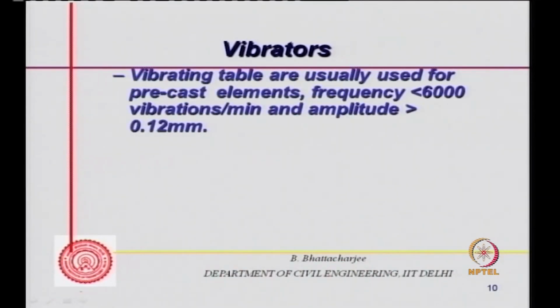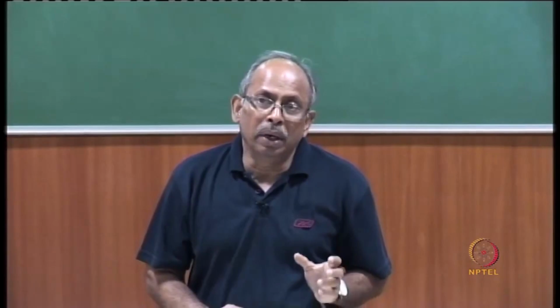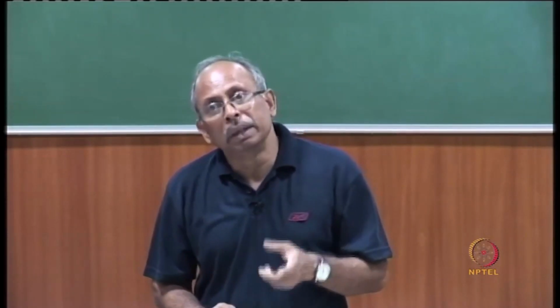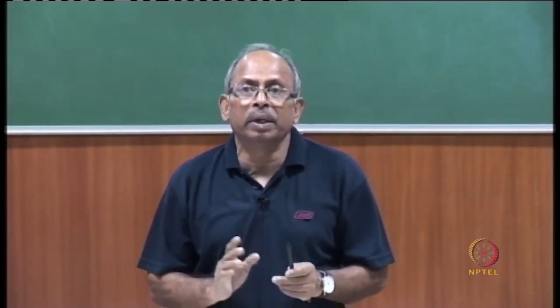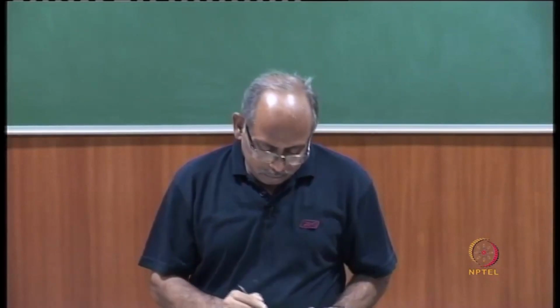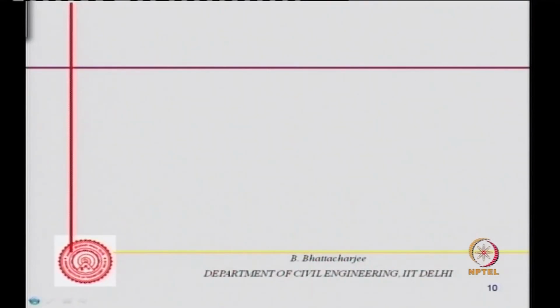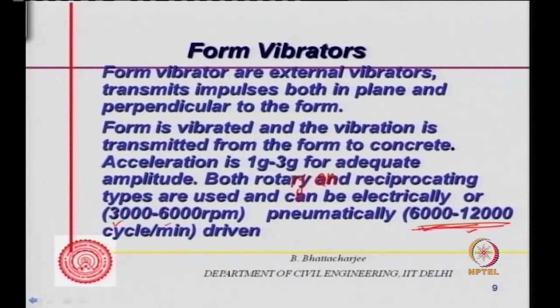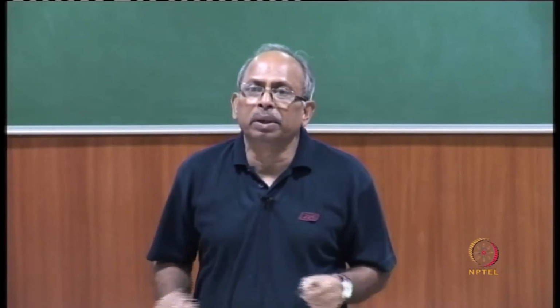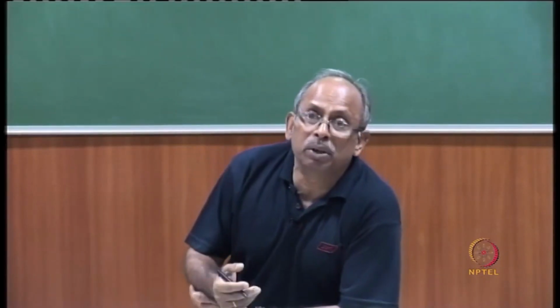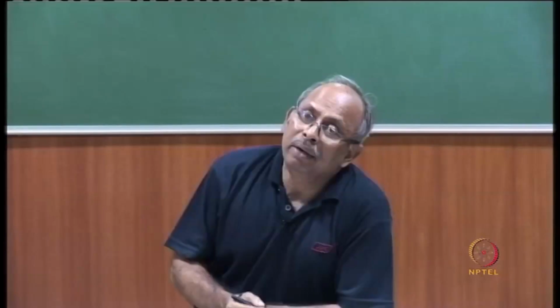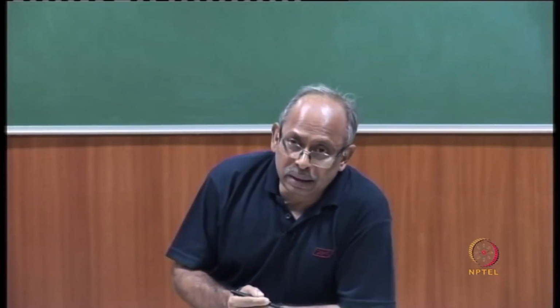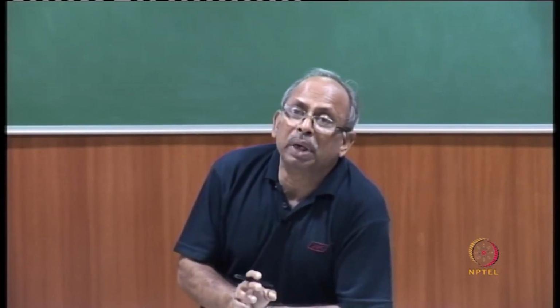So these are form vibrators. Quite often we use them in thin sections where we can't use a poker vibrator or needle vibrator, the first ones. So when we can't use them, then we can use this, or when we are using them together with those. So form vibrators are used in thin sections. It's not the best thing. Form vibrators are definitely not the best kind of vibrators, because some of the energy will be lost in vibrating the form itself. So that's not the best one. Needle vibrator obviously does a much better job because it's an internal vibrator and goes inside and compacts the concrete. Thirdly, the vibration will be limited up to a certain depth from the form only.